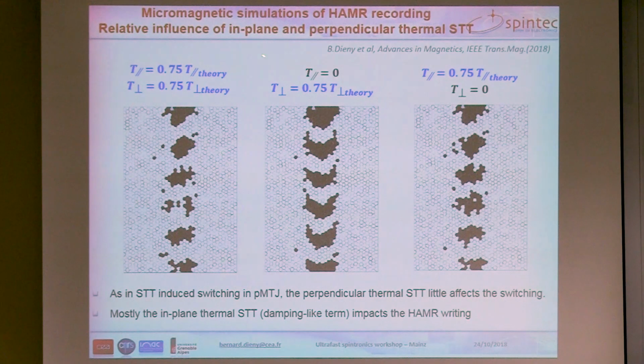If we now assume that the in-plane torque is 0 and just keep the perpendicular torque, we see that there is little perturbation of the written pattern of bits. And on the contrary, if we assume that we have no perpendicular torque but an in-plane torque, we see that we have again a strong degradation of the bits, like here. So it means that as observed for out-of-plane magnetized STT-MRAM, it's really the in-plane torque, the damping-like torque, which is controlling the switching of the magnetization, both in magnetic tunnel junction and in the media.